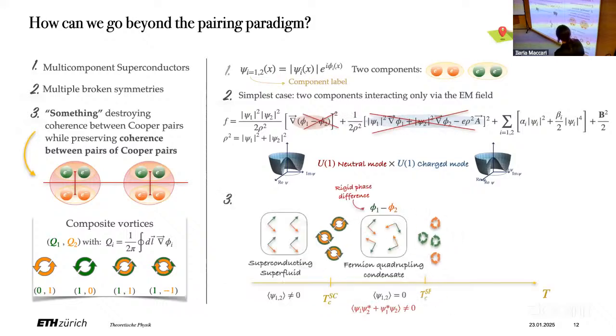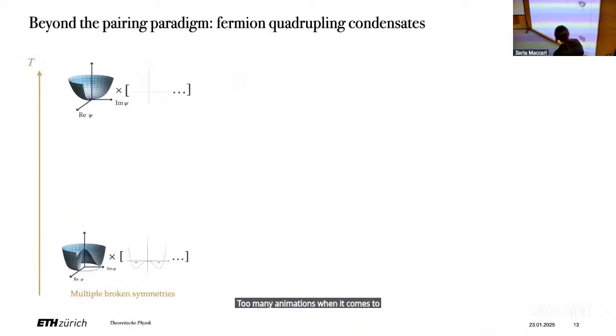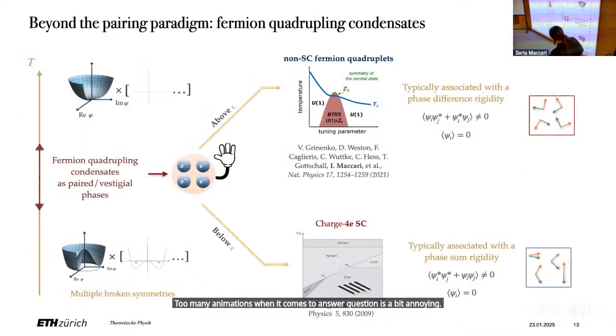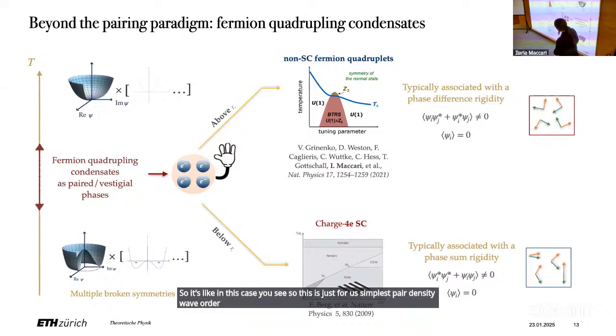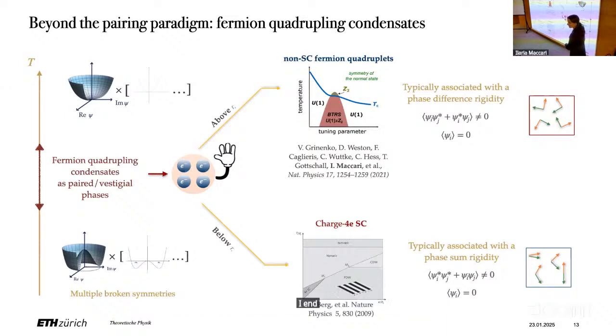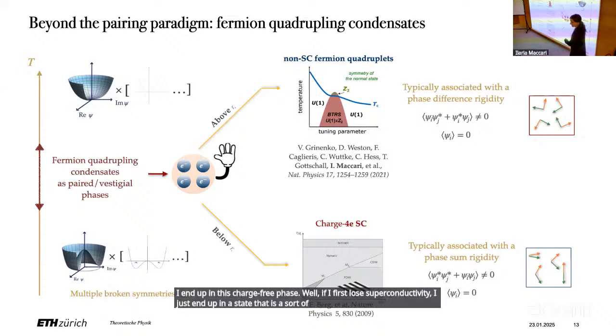too many animations when it comes to answering a question is a bit annoying. In this case, this is just for the simplest pair density wave order. And then essentially the game is, if I first melt the order in this modulation of the pairs, I end up in this charge 4e phase. While if I first lose superconductivity, I end up in a state that is a sort of charge density wave state before getting into the normal metal phase.